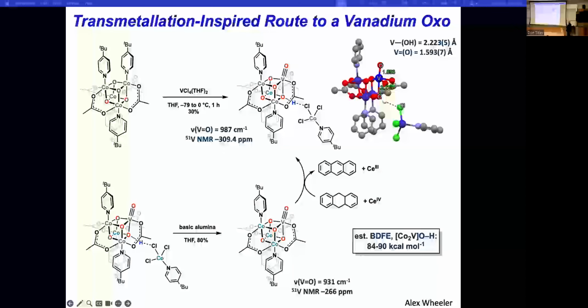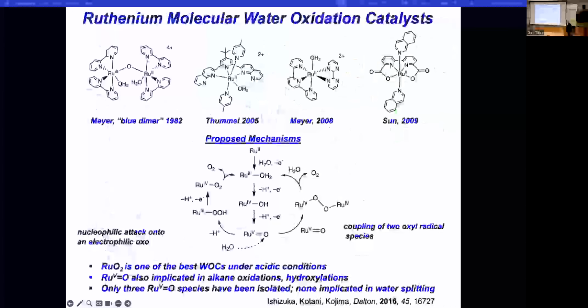The anion is the displaced cobalt 2 that you see here, hydrogen bonded in the direct product to the cube, but that can be removed with basic alumina. So we're now studying this vanadium oxo system. The cluster is harder to oxidize. So this, we think, is a pathway to making stronger bonds to the oxygen core and breaking stronger bonds in substrates. That's the main pathway we're taking for that. The other metal that we've introduced with some success has to do with ruthenium.